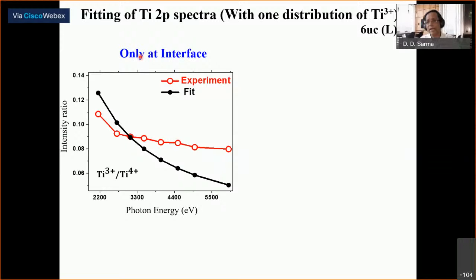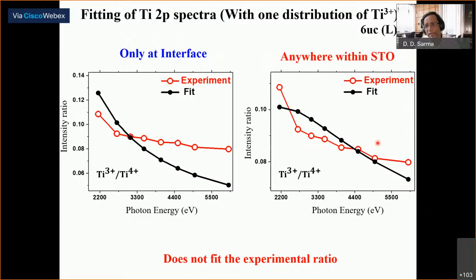And if we imagine that this extra charge density, the titanium 3d electrons, are tied to the interface with whatever thickness, starting from the interface and going down with uniform concentration, the best fit that I can get is given by this black line. And the experimental data is here, and it shows that if I imagine that my charge carrier density is tied to the interface with one simple distribution, there's no way I can describe my experimental variation. So if I imagine, let it not be at the interface, let it be anywhere, a constant distribution anywhere in the STO, this is the best that I can describe, and it still doesn't fit my experimental data at all, which tells me that with one single distribution, I cannot fit the experimental variation.